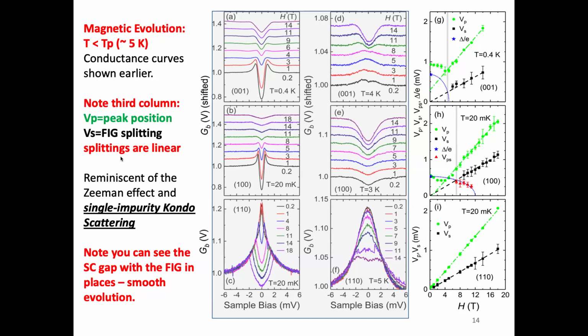Yeah, so we don't know. I know that when I was studying this years ago, if you're tunneling into a magnetic semiconductor, you can get huge g's. Typically in a metal you don't, but these are spin orbit coupled f electrons, so they're going to have much bigger g's than normal. And you're only measuring the electrons that get through. I think that's a really good question, because now that you bring it up, all you're measuring in tunneling is what the electrons look like when they get through.